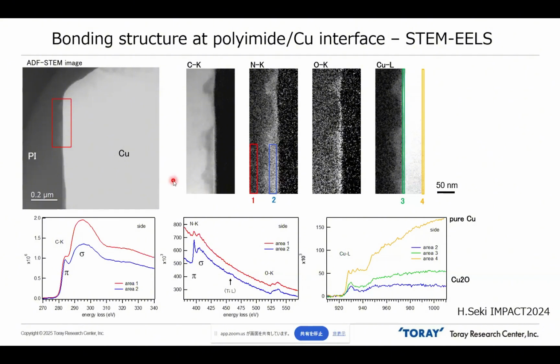Then we got EELS experimental data from the same sample. Even in the EELS two-dimensional map, we can find nitrogen has higher intensity around the interface between polyimide and copper. Then let's see the bonding structure by using peak structure. At first, let's see the copper peak structure. Area 4 means the inner part of copper. Area 3 means just the interface between copper and polyimide. Area 4 shows pure metallic copper, but the peak structure of area 3 is much different from the inner part of copper. This peak structure shows copper oxide.